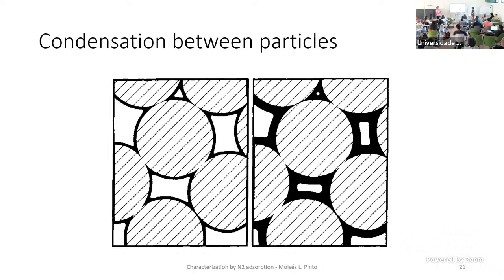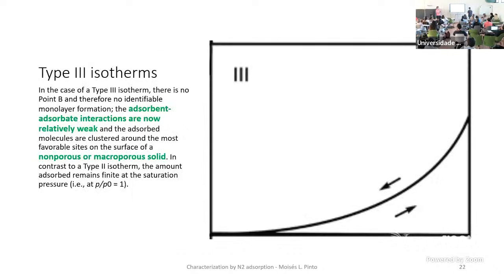And another type is the type 3 isotherm, when we have low interaction between the adsorbent and the adsorbate. So in the example I have shown, for instance, for water in activated carbon, the water doesn't like to be at the surface, so it does not adsorb unless you increase the pressure.